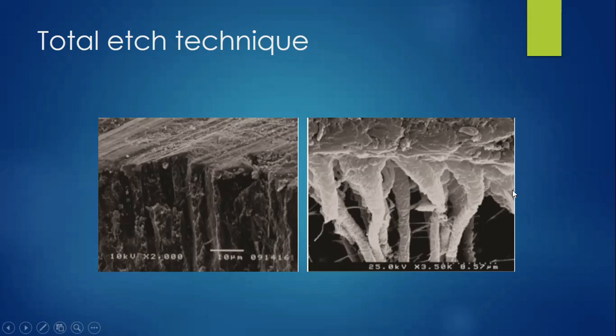It can lead to nano-sized porosities on the bonding interface. These nano-sized porosities impair the monomer conversion, affecting the mechanical properties of the adhesive layer. What we call nano leakage occurs because of the fluid dispersion through this, creating a nano space on this interface. Increase in nano leakage expression is more frequently linked to the use of 2-step etch and rinse systems compared to 3-step. Therefore, 3-step is said to be the gold standard.